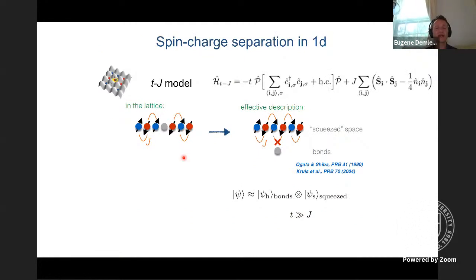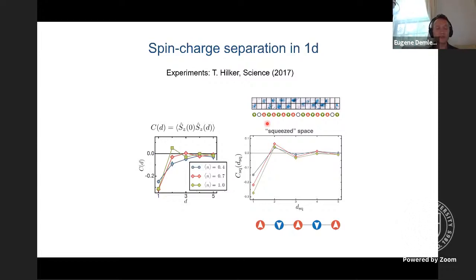But in fact, one can prove an even more general theorem that when we take these 1D Fermi-Hubbard models at finite doping, we can take the many-body wave function and remove all the holes. And when we remove all the holes, we just end up with sites where there are spins, and the wave function on this squeezed space should be the same as if holes were not there. So somehow in squeezed space, spin correlations are the same as at half filling. But of course, to think about such a measurement, you have to be able to know what's happening on every site, and that was not accessible in traditional solid-state systems, but that's what can be done in cold atoms. And this is actually shown beautifully in this data from Bloch's group.